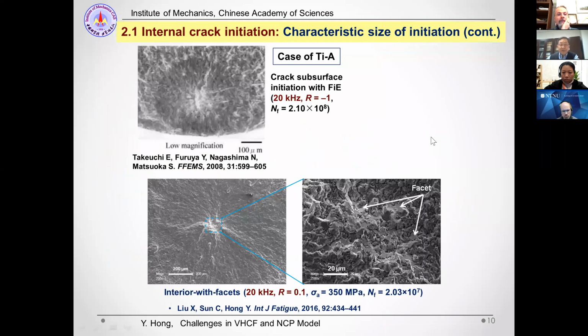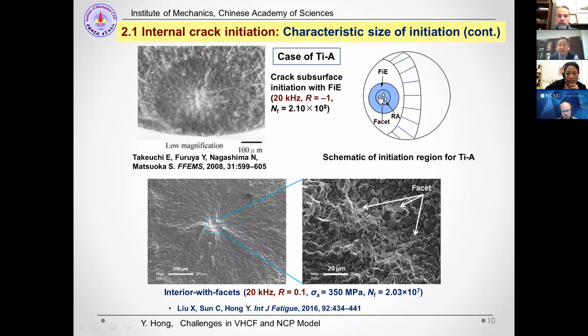And then I would like to talk about the case of titanium alloy. The crack initiation is also a fisheye feature, but for titanium alloy, the initiation site is not an inclusion, but is some facets in the initiation area due to the cleavage process of the titanium alloy, always alpha phase. And this is the schematic showing this process. The formation of facets act as the crack origin, and then the area called RA as crack initiation region, and then the fisheye region, and then final fracture.